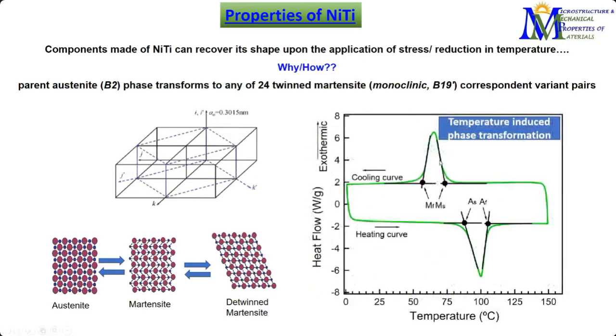All this phase transformation achieved with stress can also be achieved by changing the temperature. At one particular temperature it changes from austenite to martensite, and if we reheat it, we can get back to austenite. So this is a completely reversible hysteresis that can form. As I said, it is used in niche applications like lunar vehicles, but most commonly this material is biocompatible, which is why it is also used for various medical applications and implants.